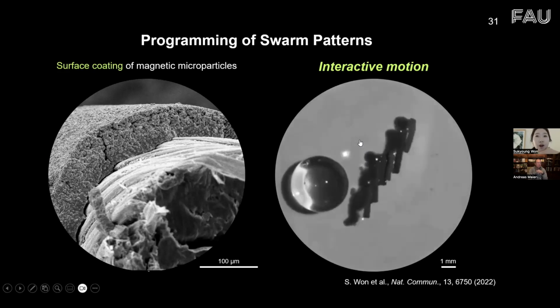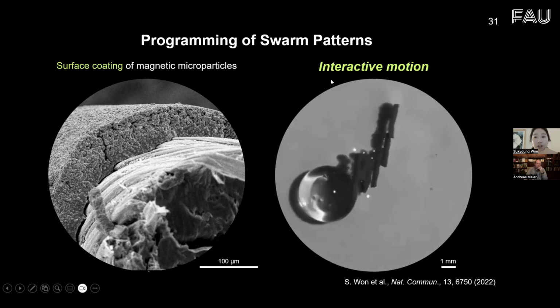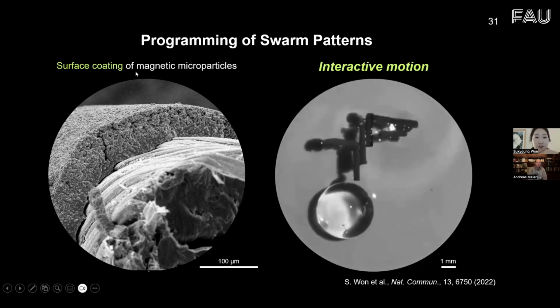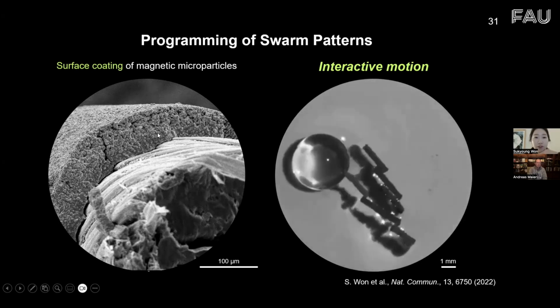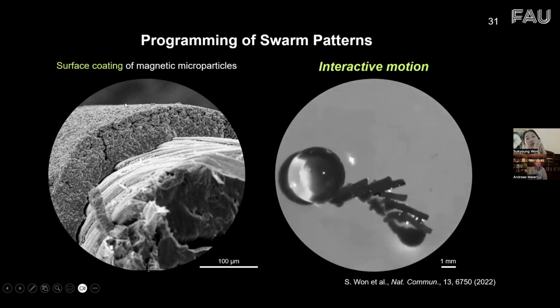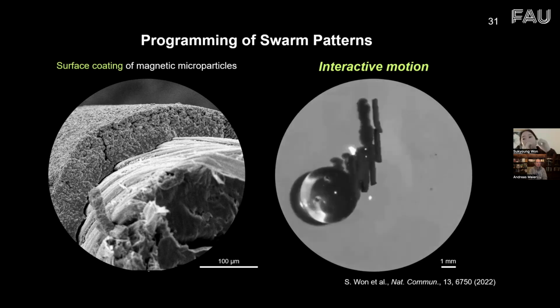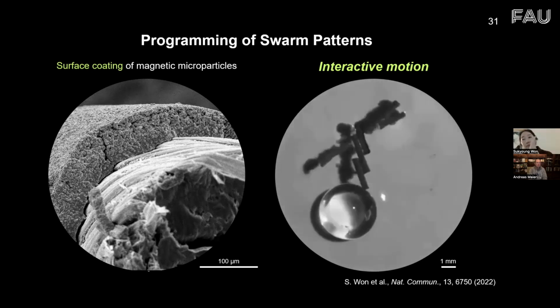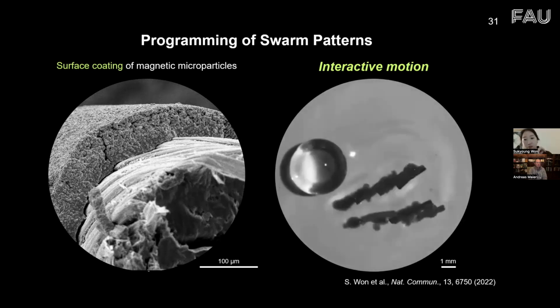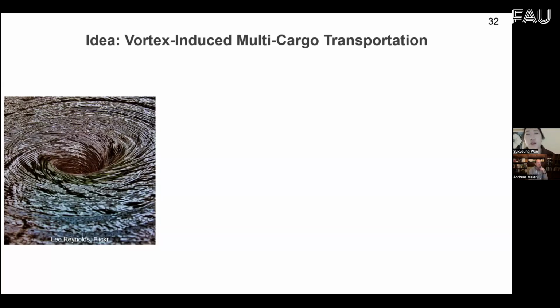So, how about the application of the interactive motion of multiple robots by surface coating of microparticles onto the robot surface? Because they decrease the interparticle distance, we can get a higher magnetic attractive force between the robots, so we can control the magnetic assembly of multiple robots. This assembled structure is for vortex-induced cargo transportation. Previously, many grippers demonstrated multi-cargo transportation with precision control. However, when the cargo numbers increase to the hundreds or thousands, simultaneous transportation is difficult and time consuming.